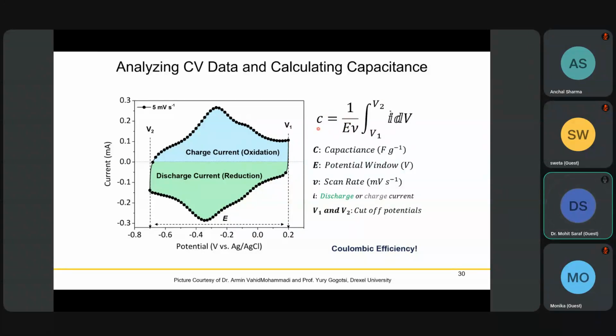You might see some formula where they divide by 2, that is just because you have two different sections, so you can use this formula. Basically we calculate this area under the curve, and then we divide it by scan rate and your potential window. It should be noted that when you do this, the Coulombic efficiency should be good enough, then only this formula applies. Otherwise there will be a difference between the capacitance you got here and what is obtained here.